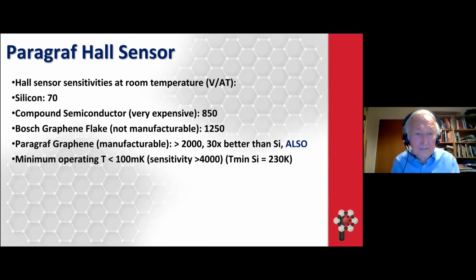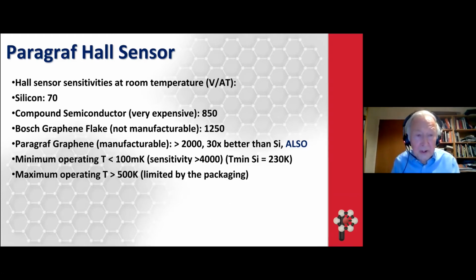Maximum Hall temperature operation is about 500 K, and that's not limited by the sensor itself, not by the graphene. It's limited by the packaging on the material. So if you can improve the packaging, you can improve this maximum temperature. It's very radiation resistant, and has a very high magnetic field range, from -14 Tesla right through to +14 Tesla. And that's the highest that we've measured so far.